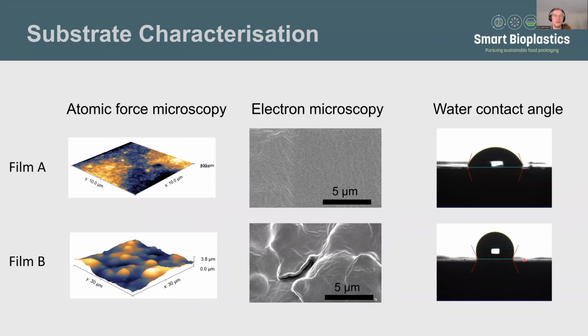And if you imagine you spray onto the surface, you get little distinct droplets that would then create islands of bioparticle deposits, but not a coherent film. Versus in film A, it's a much rounder droplet with much shallower angles. And again, if you imagine spraying this, the droplets can much more easily coat a much larger area and create a smooth, coherent film together, which is much better for an even distribution of those bioparticles.